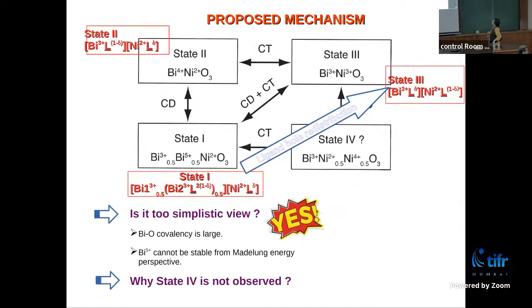So our proposed mechanism is shown in red, and in black was the mechanism proposed by the solid state chemists. We feel all their things should be replaced by just the ligand hole story and nothing else. Bismuth and nickel are not doing anything. Bismuth likes to be in 3+, nickel likes to be in 2+, and it is just the ligand hole that is doing all the music. So indeed, our answer is a too simplistic view.